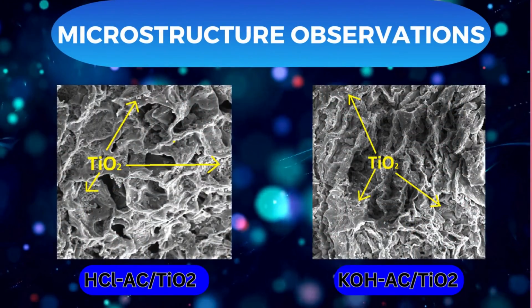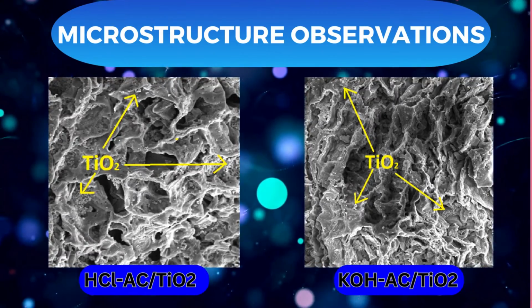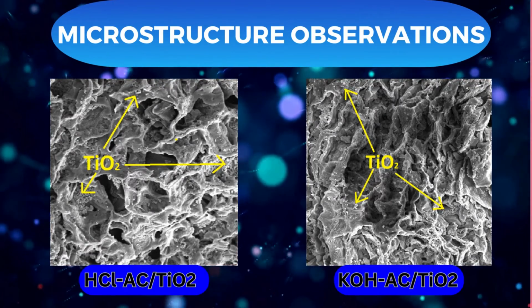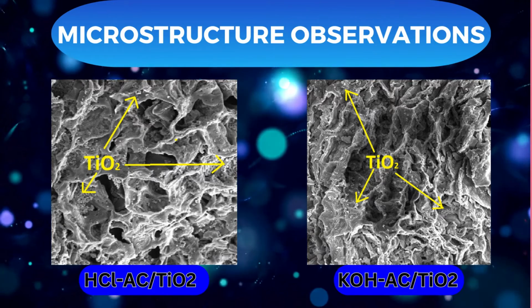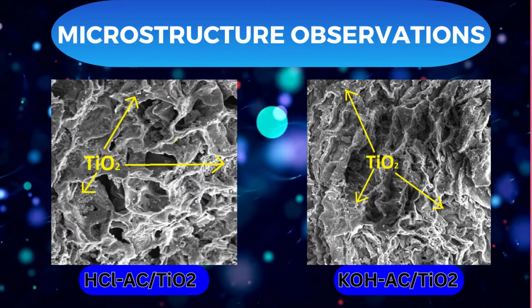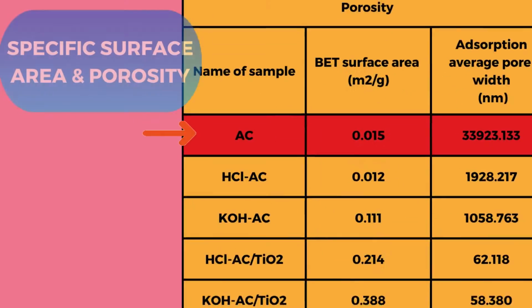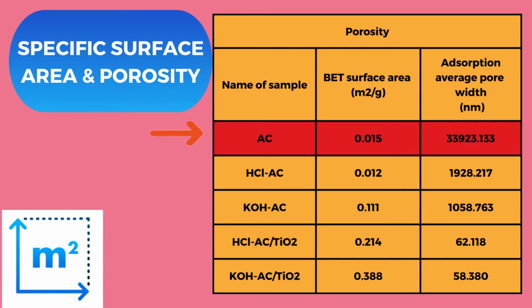The morphology of Titania activated carbon composite reveals the presence of TiO2 nanoparticles effectively attached to the surface of the activated carbon within the micropores for both treated activated carbon samples. Activated carbon shows the highest average pore width, which provides a reaction site that acts as an adsorbent. Acid-treated activated carbon has a larger pore size compared to base-treated activated carbon. The larger pore size provides sufficient active sites for MB dye adsorption. However, the pore size decreased after the addition of Titania photocatalyst because the TiO2 covered the pores.